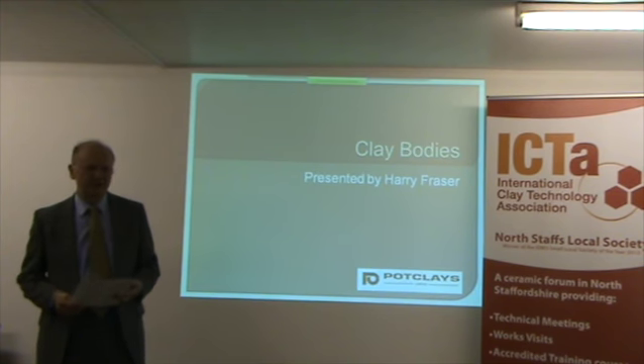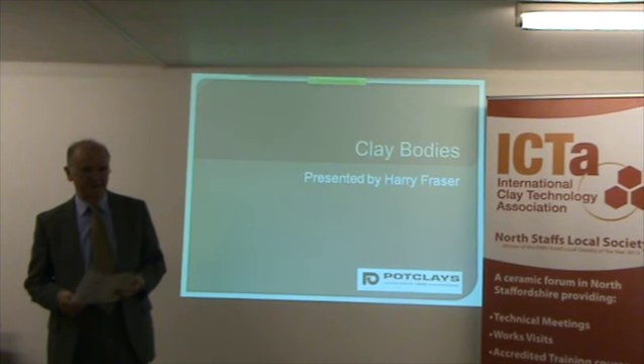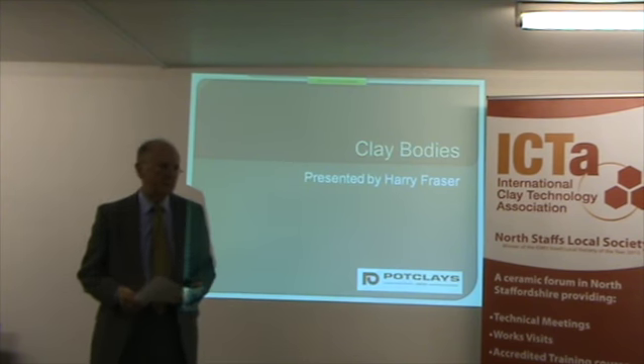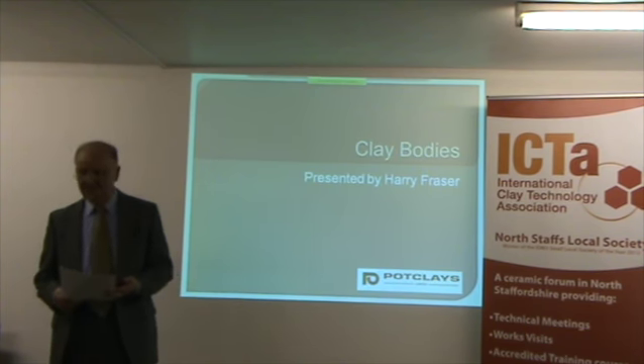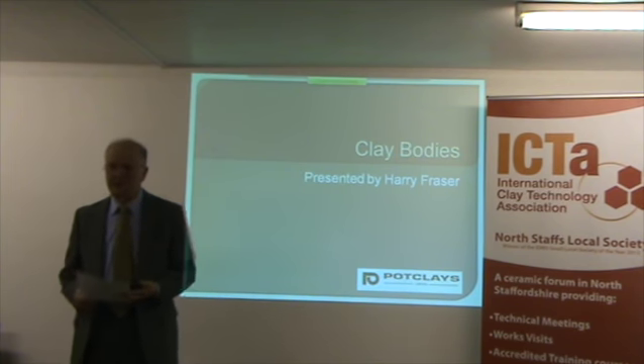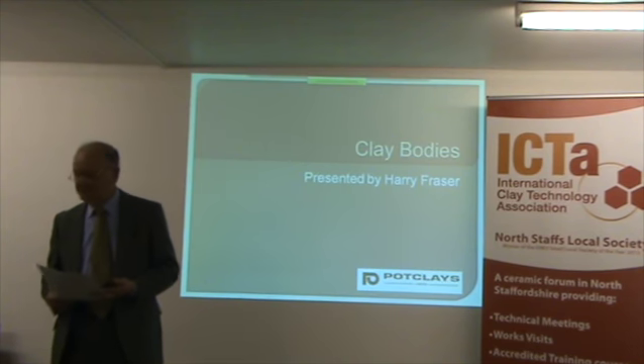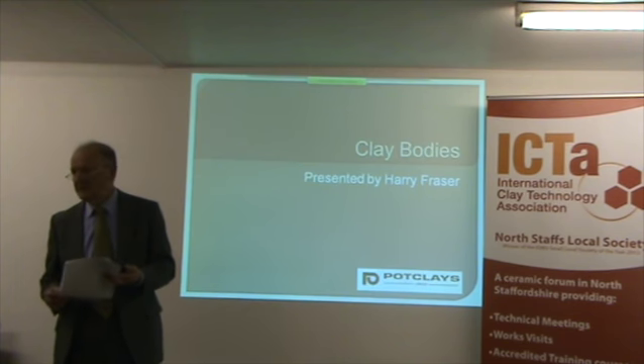Now, clay isn't a very good engineering material. It's got some very awkward properties. It shrinks as it dries, and it shrinks again as it's fired. And if you don't dry it evenly or fire it evenly, it may warp or crack. And the more plastic a clay is, and the softer its consistency, the greater are those problems. And so in industrial pottery production, we generally seek to minimize those problems by using clay bodies of low moisture content and or low plasticity, or use dust pressing, allied to careful drying and firing techniques. And if we need to make some complex shapes, we use slip casting, where we don't need any plasticity, it doesn't enter into the equation.